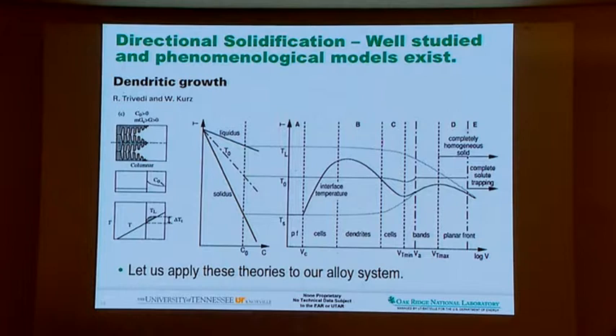If you have a phase diagram, T versus C, you would expect equilibrium conditions, where if you're coming down here, that's where the solid will form. But that is assuming a very low velocity. What would happen if the velocity is increasing? The interface will never be planar, it'll create dendrites, and then you need to worry about the dendrite tip temperature, which goes up and down because of the instability criteria. If you have a solidification book, go and look for these two magical people, Mullins and Sekerka. They developed the theory for that.